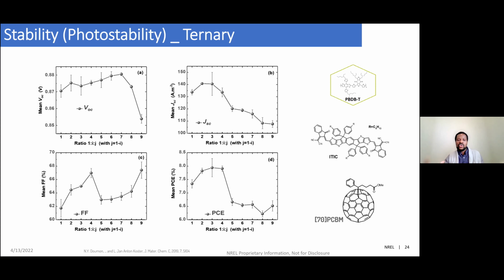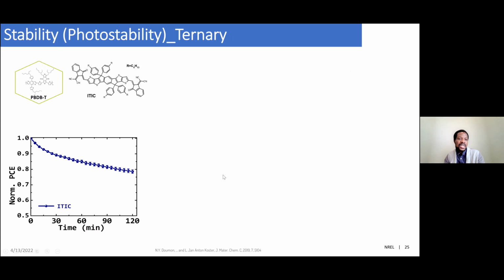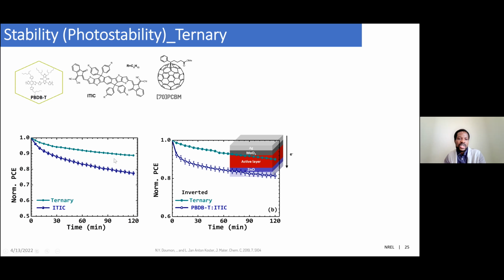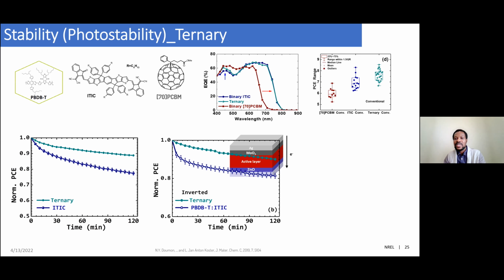problem. So what you have to do is to try a lot of ratios, and of those ratios, you will begin to see at what ratio you have the best result. And our best results are around these 3 ratios. And all 3 of them gave us the best efficiency and also the best stability. So we decided to stick with one of them. And here clearly you can see that ITIC has shown already a degrade over time, but when you start introducing your [70]PCBM, you see a slight improvement in the device stability, whether in conventional or inverted structure. And that improvement is not only seen for stability, but it's also seen in the device efficiency, which is good news.